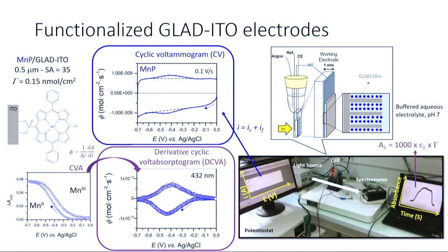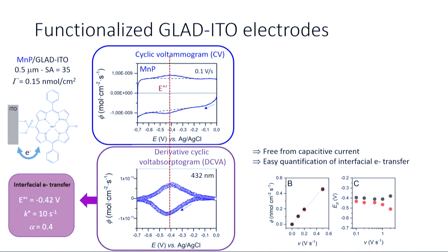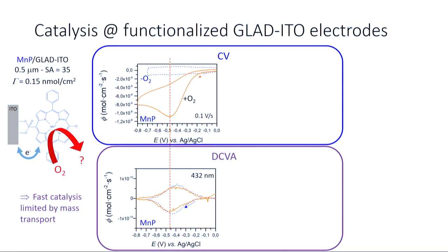This is what we call a cyclic voltabsorptogram, so absorbance versus potential, and if we differentiate this versus time, we get what we call a derivative cyclic voltabsorptogram. What you notice here is that this is morphologically equivalent to a cyclic voltammogram, but free of capacitive current, because you just focus on the electroactive chromophore. So based on this, you can make an easy analysis of the interfacial electron transfer process, even at low surface coverage of the immobilized redox probe, and you can quantify and get all the information about this reversible electron transfer.